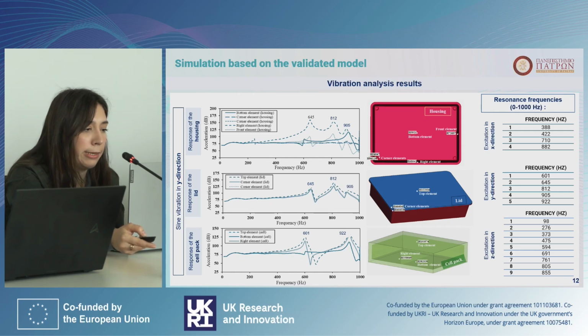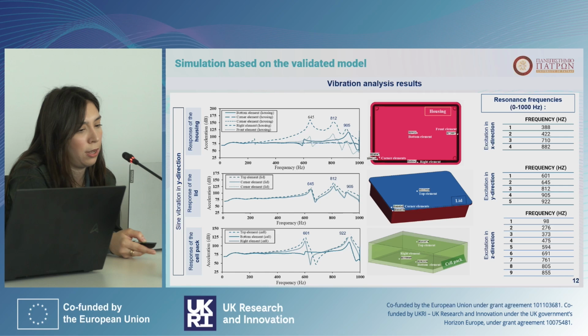For the vibration analysis results, the resonance frequencies are identified for each of the three excitation loads and each of the three directions of loading. The outcome of the vibration analysis is evaluated by identifying the resonance through the peaks of an acceleration frequency curve. Elements from the finite element model of the components have been selected based on the symmetry and the geometry of the components. The graph includes the curves of a single component, the housing, the lid, and the cell pack, to identify more effectively which resonance derives from each of the three.